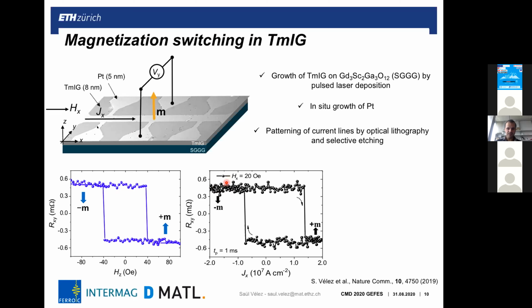This is what I'm showing here: if you apply a magnetic field in this direction, you break the symmetry of the system and then stabilize either up for positive current pulses and down for negative current pulses, because of the symmetry of the effect. Now, if we reverse the orientation of the magnetic field applied in plane, we can stabilize up domain walls by sending current pulses with negative polarity and down magnetization by applying positive current pulses.